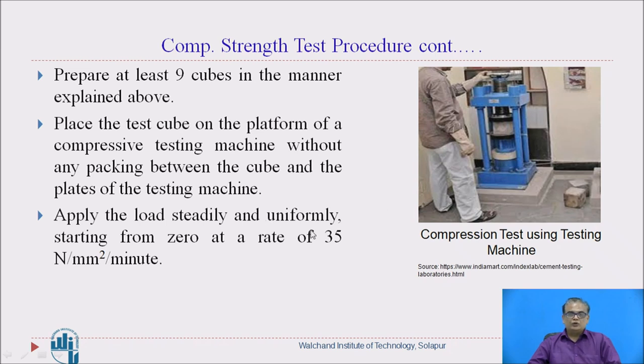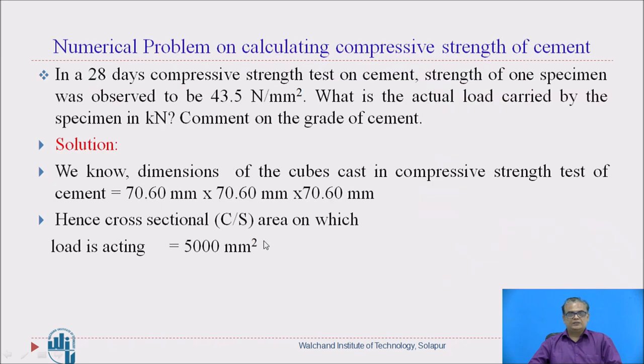The rate of loading should be uniform at 35 N/mm² per minute, as specified by the IS code.